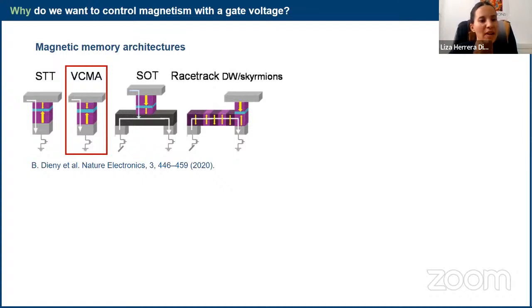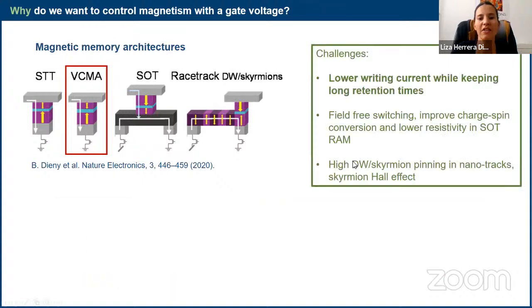And we can find different things. For example, in particular, SOT requires a larger improvement of charge to spin conversion, or field-free switching, or in the case of the racetrack, for example, to better control the pinning and motion of domain walls or skyrmions in tracks.